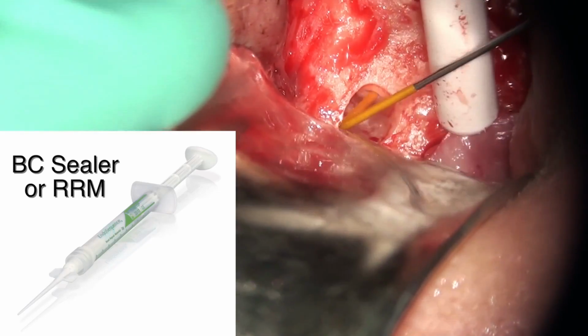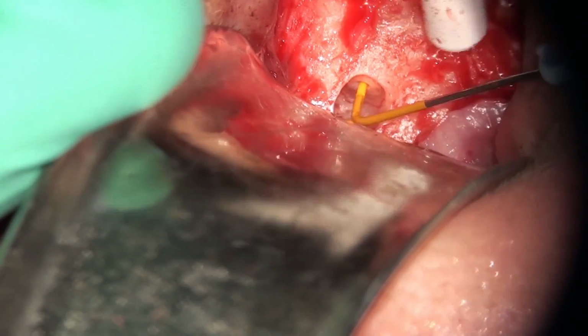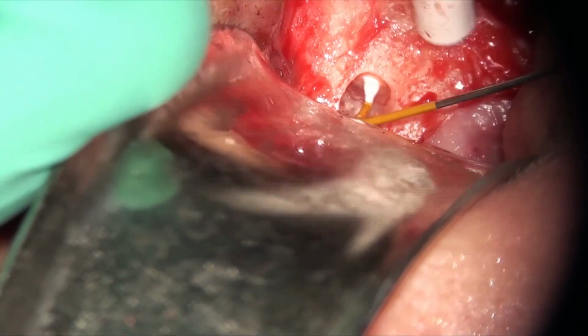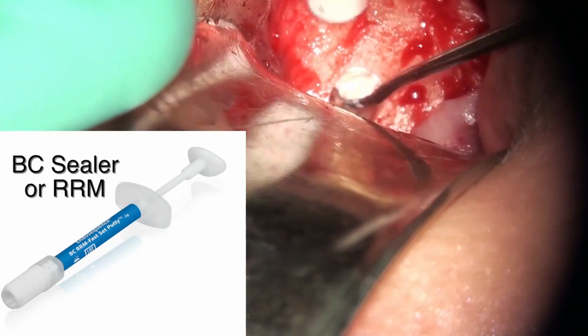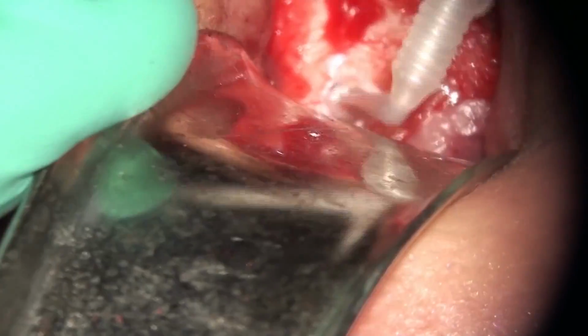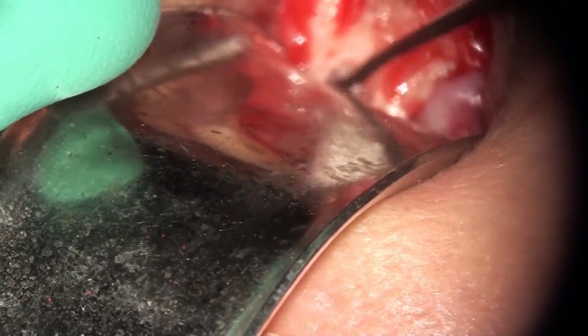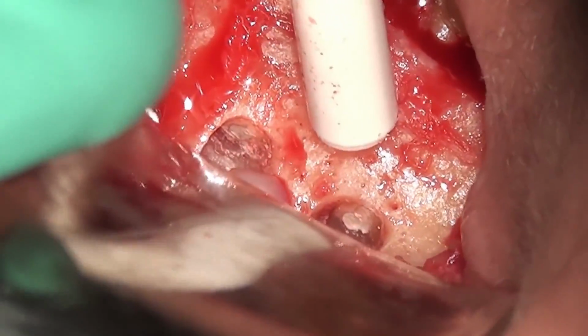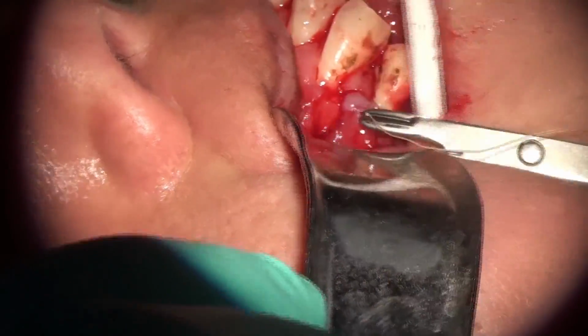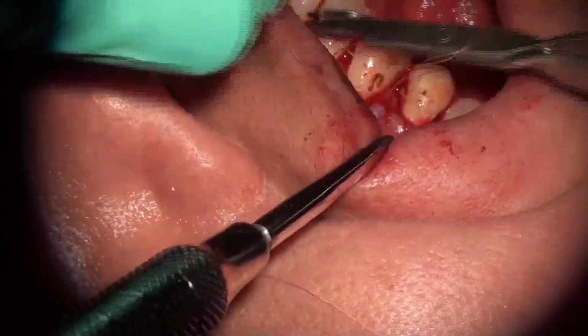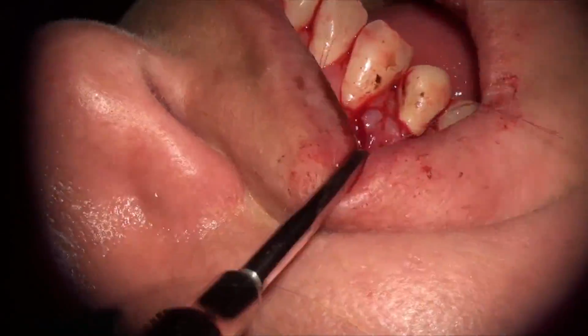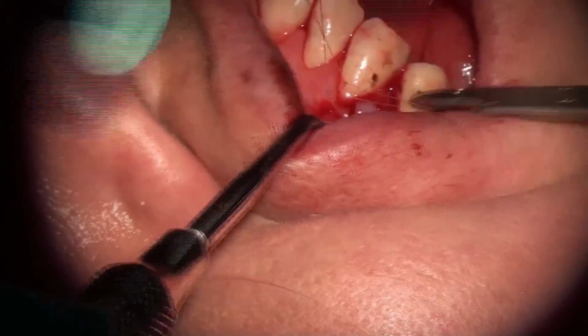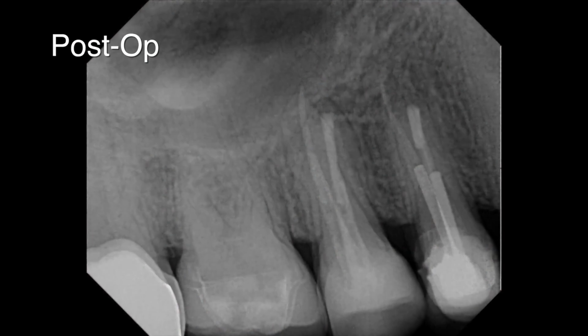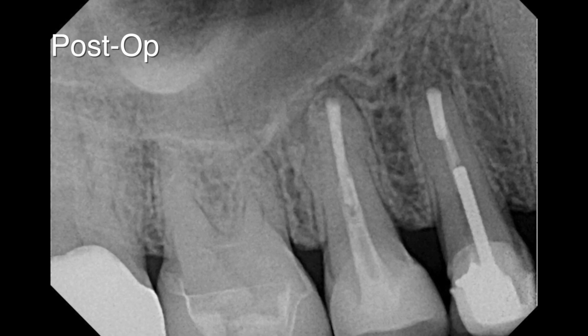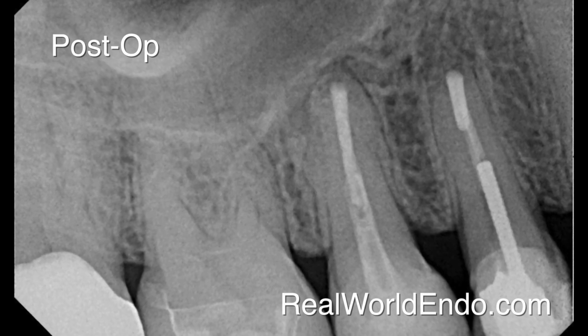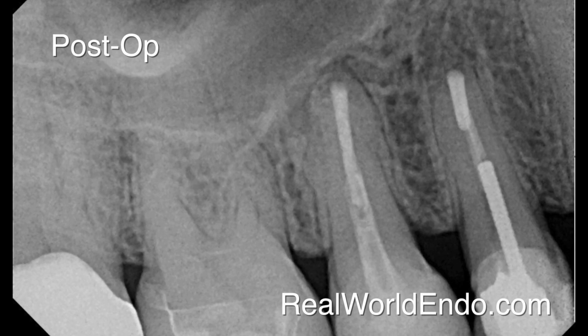So you can see the second one is done, and now we do the first premolar in the same exact way, injecting the light body syringeable material, followed by very quickly proceeding to place a little ball of the putty in there, and then remove the excess with a micro brush, and then using a little bit of water to clean out any debris. And you can see very quickly that we did both of those 2 teeth, and now it's time for the suture placement. I use gut sutures because they're self-resorbable, and the patient doesn't have to come back right away, and we can follow up. This is a pre-op and then a post-op, and as you saw very quickly, 2 apicoectomies on these 2 teeth were done, and the patient did very well with them.